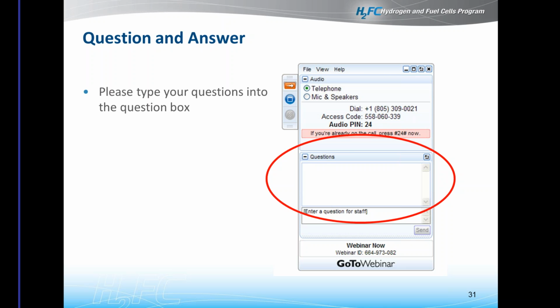A couple of questions about impurities. I think maybe you sort of answered some of them towards the end, but one of them was why the choice was made to use high purity hydrogen gas rather than a lower quality to better simulate what's put in the field. And then another one was whether it's likely that impurities of other gases other than oxygen would similarly slow down crack growth. Yeah, those are two very good questions. The real reason we started looking at pure hydrogen is we really wanted to see the worst case scenario. We wanted to be as conservative as possible and look at what the extreme environment would be, which would be pure hydrogen without any impurities.